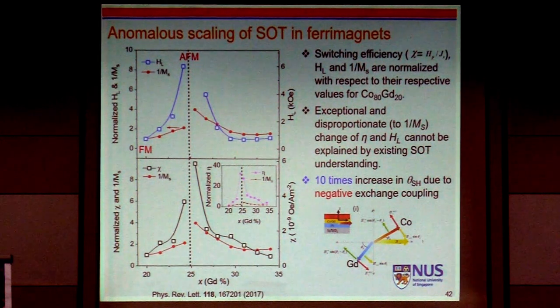regime. And we attributed this to negative exchange torque. Earlier, IBM introduced this negative exchange torque concept in their synthetic antiferromagnet. So then they reported very high domain wall velocity up to 750 meters per second. But in our case, we now bring in this antiferromagnetic coupling in an atomic region because we just put alloy.